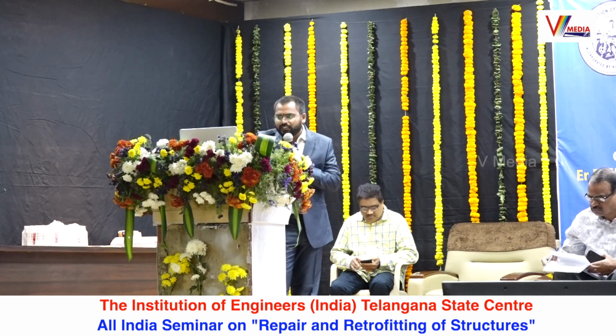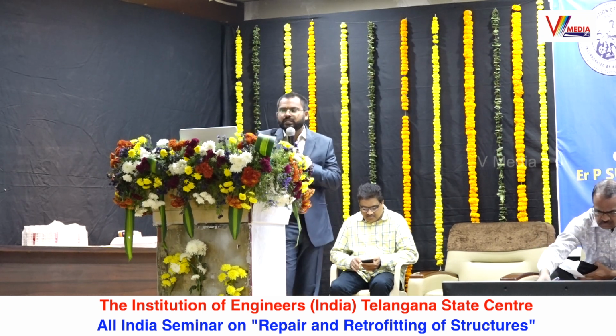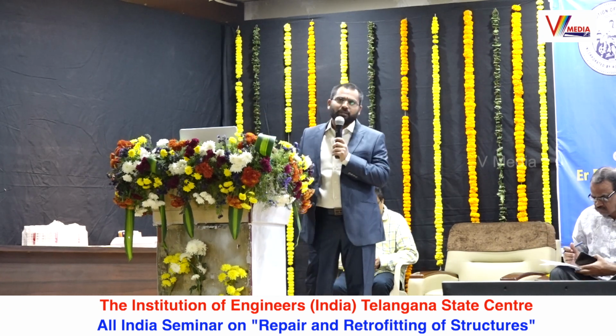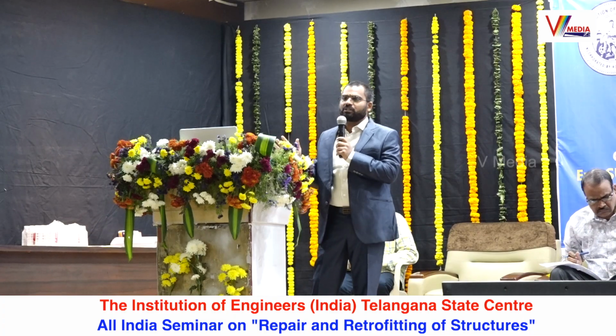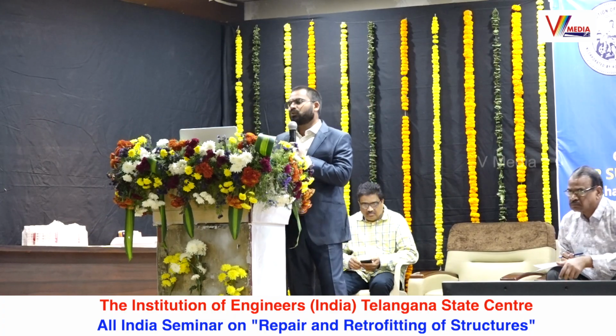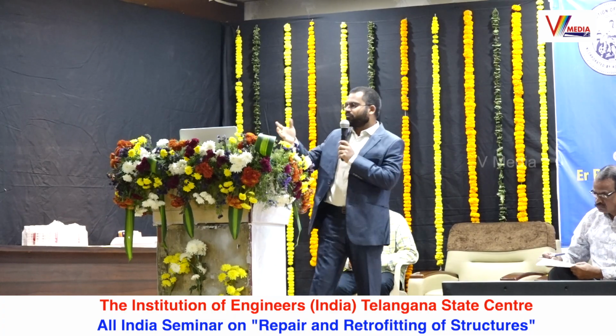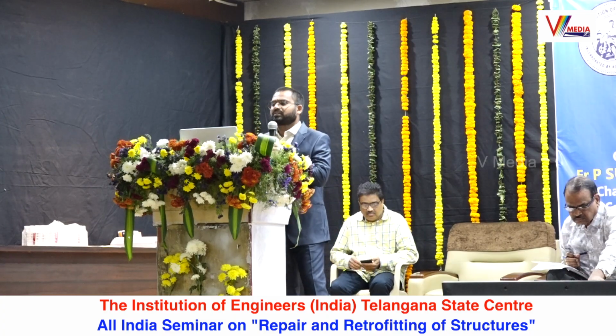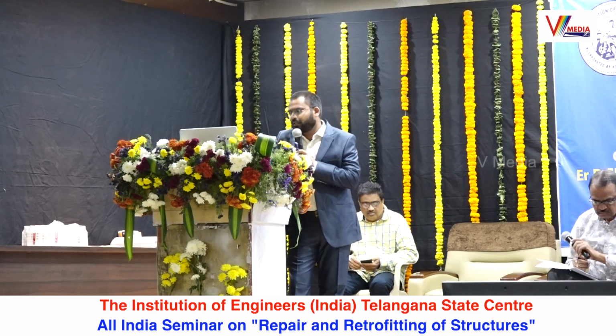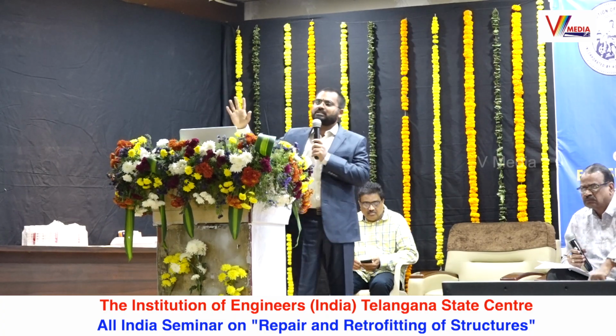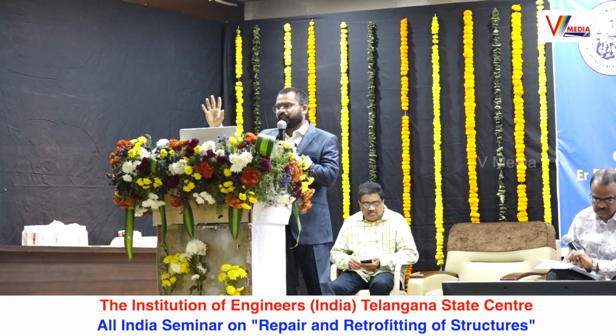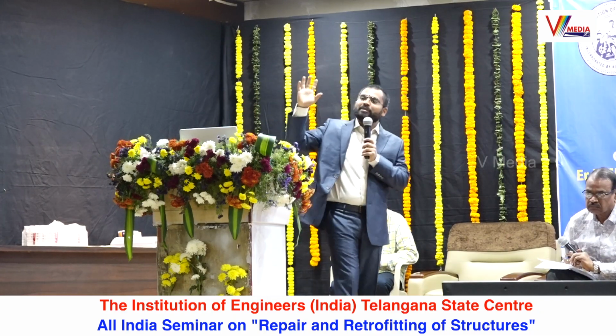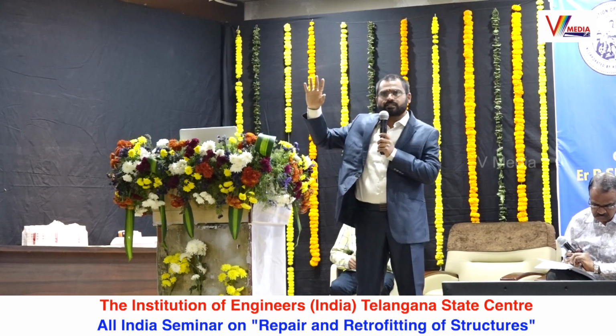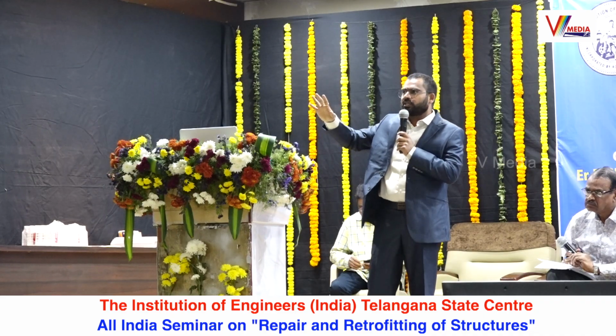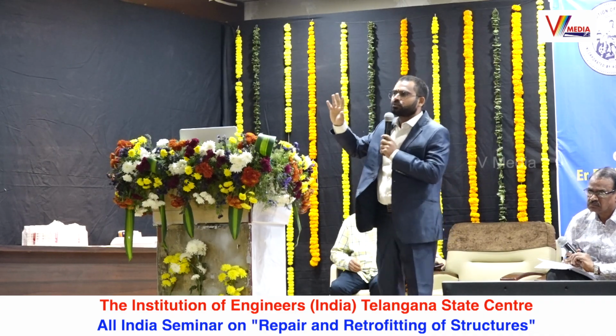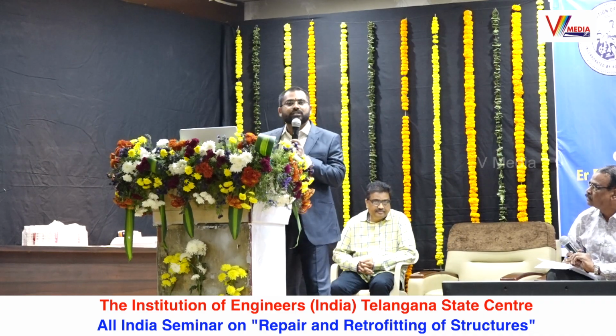Okay. There are some correction factors. It is based on the instrument manual. We have many manufacturers in the industry, so whatever instrument you are using, you have to apply the respective correction factors which are given in the instrument manual. Okay. There are some factors affecting the rebound hammer. Type of aggregate, age of concrete. Your minimum age for testing NDT is 14 days. Once the concrete is cast in the structure, only after 14 days you are supposed to do the NDT. Then surface condition.